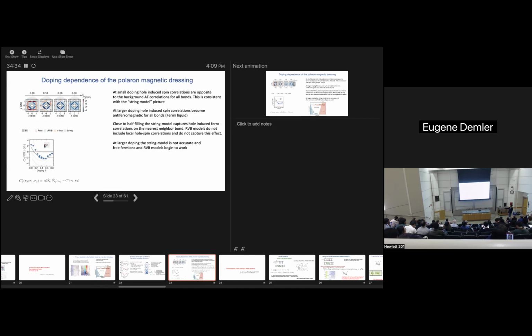So these kind of averaged approaches actually work quite well for strong doping, but they fail when we talk about the weakly doped regime. In particular, they don't even show the change of sign of correlations. So we clearly see that this microscopic model, based on a local picture of spin correlations modified in the vicinity of holes, works at small doping, whereas at larger doping we go to the regime where traditional condensed matter mean field type approaches work.